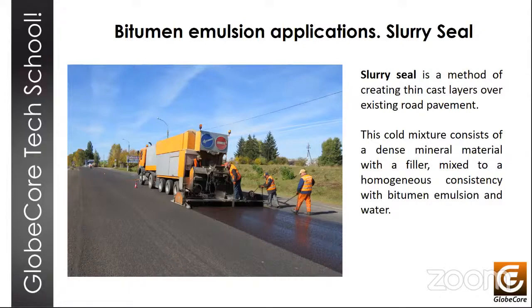Microsurfacing emerged as a further development of slurry seal technology, and with its help, a sufficiently thick and durable coating is created. Microsurfacing can be applied in 2 layers of 25 to 30 millimeters, and in some cases the total thickness reaches 75 millimeters. With microsurface technology, larger stone material is used, and the bond is stronger than slurry seal, so the coating can withstand fairly heavy loads without deformation. For better shear stability, latex is again introduced into the mix.